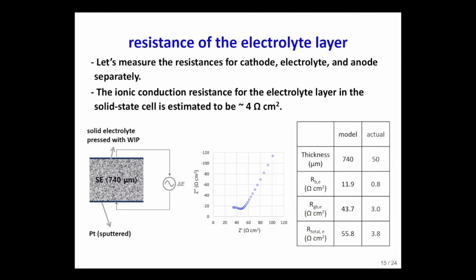The easiest part was the electrolyte layer. We just prepared a solid electrolyte pellet and pressed it with a warm isostatic press. Platinum was coated on both sides of the pellet. The total resistance measured in this way was about 56 ohm centimeters squared. Since the thickness of the electrolyte layer in our solid-state battery is only about 50 micrometers, we can estimate that the resistance for the electrolyte layer would be less than 4 ohm centimeters squared in the actual cell.